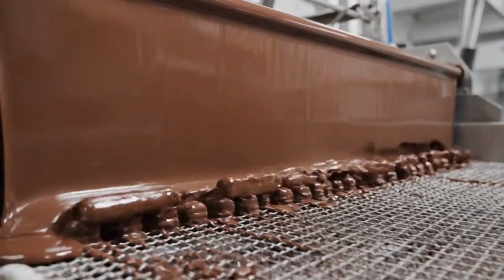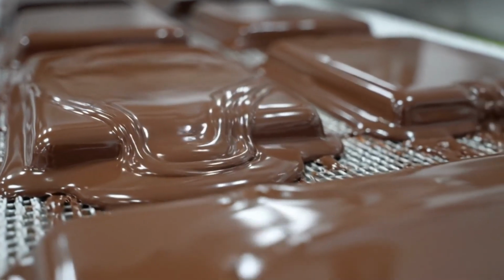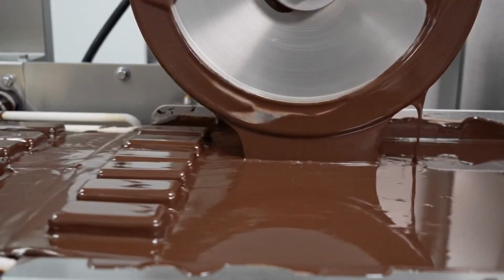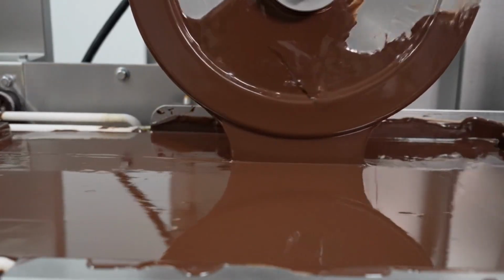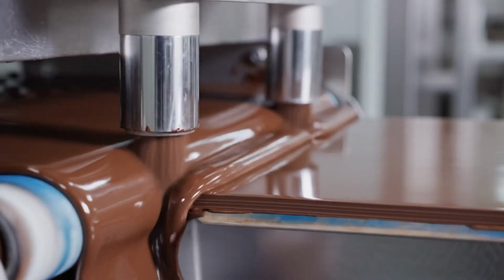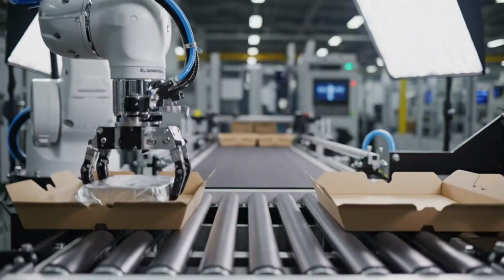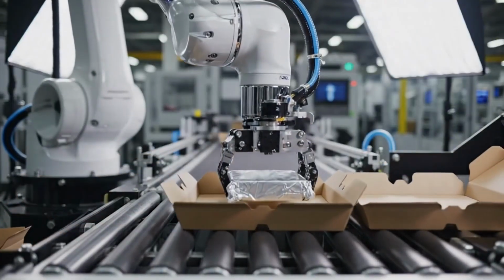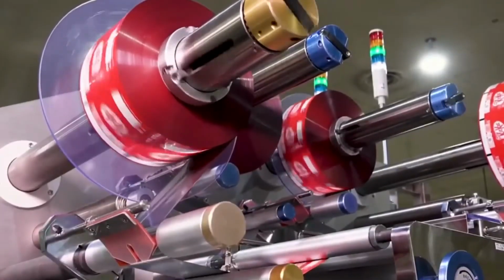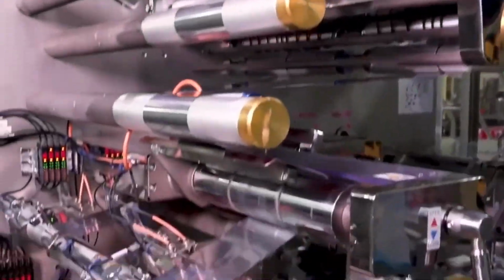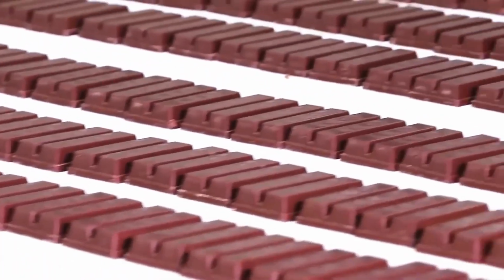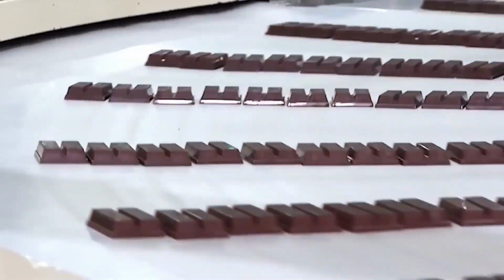They travel single file on a mesh belt through a curtain of liquid chocolate. The chocolate, now tempered, falls at a controlled rate and coats the top and sides of each bar. The underside is coated by a roller mechanism submerged in the chocolate reservoir. 3 coating passes are applied in sequence, each adding a layer between 1.5 and 2 millimeters thick, for a total external coating of approximately 5 to 6 millimeters. After the final pass, excess chocolate is blown off by an air knife to prevent pooling at the base edges.